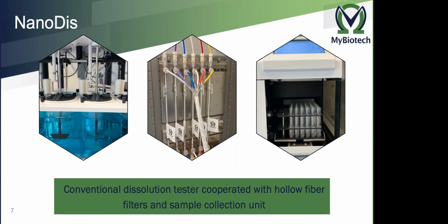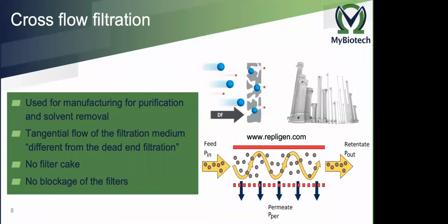What happens is basically the sample is taken from the dissolution vessel with a pump. It goes to the cross-flow filtration module. The medium without particles is filtered out of the cross-flow filtration module and taken through another pump into the sample collector, and the dissolution medium which was in the filter module is directed back into the dissolution vessel, so that we are also not losing any dissolution medium.